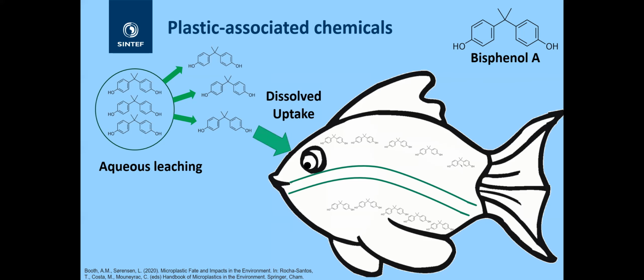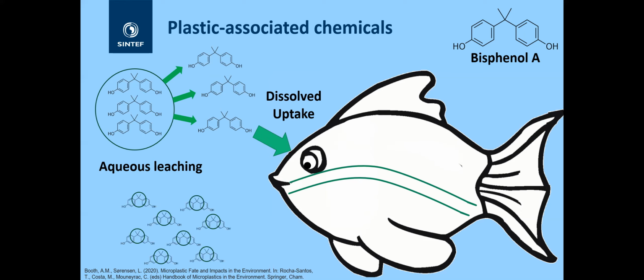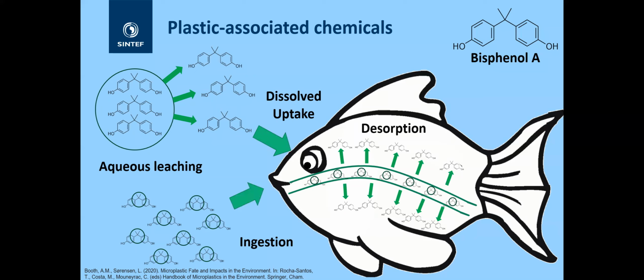And when that happens, if there are organisms present, then you would get what I would consider a conventional exposure scenario for the chemical. It's in the dissolved phase, the fish or any other organism is swimming through, and there's this exposure and this potential for the chemical to be taken up and potentially accumulate and cause a toxic effect. But when particles are present, there's also a secondary exposure route, which is the direct ingestion of the particles containing the chemicals and the potential for these chemicals to leach out during transit through the gut of the organism, like this. So we still don't know how important this route is, but at least it is a potential.